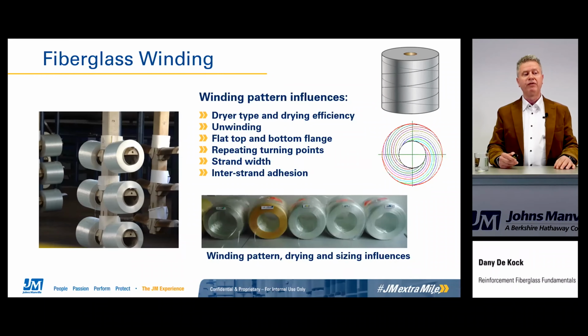And if you look at the winding pattern, if it is not correct, it can cause collapsing of the bobbin. On the right side of the picture below, you see a deformed bobbin, which can cause issues at customers, because when they start pulling out the roving, it collapses and creates a bird nest, and they have to stop the process because the fiber is breaking, or the bird nest is blocking further pull through their systems.